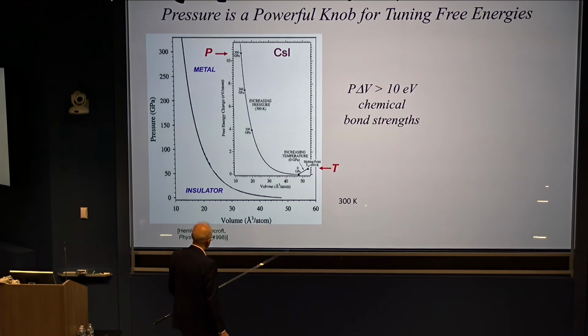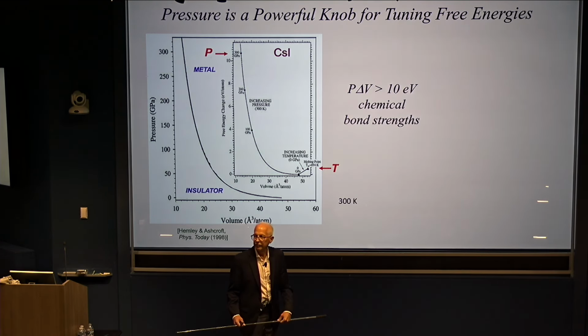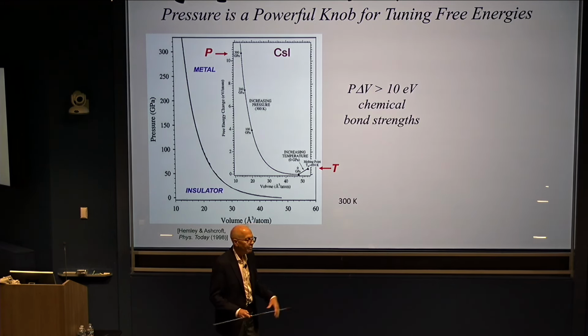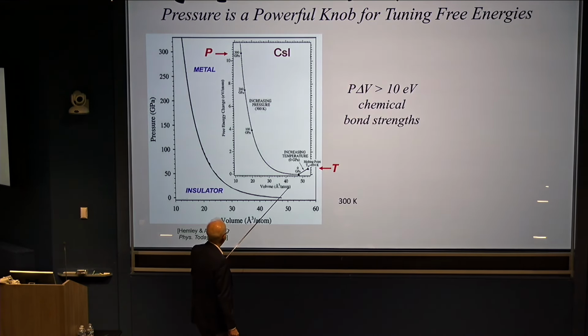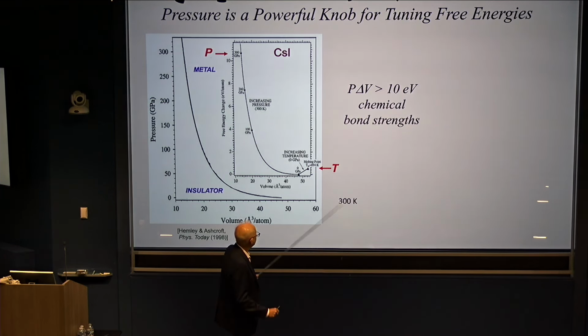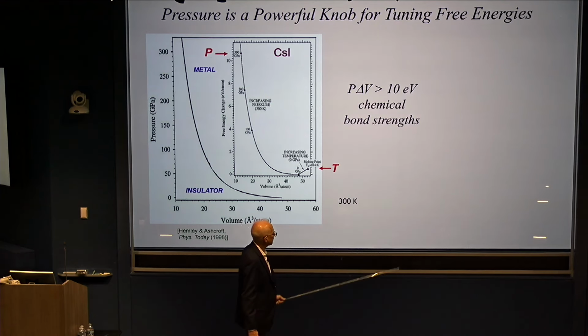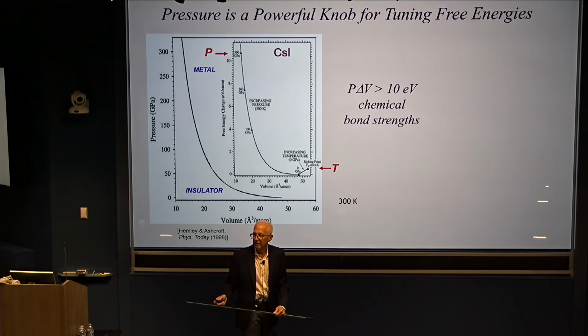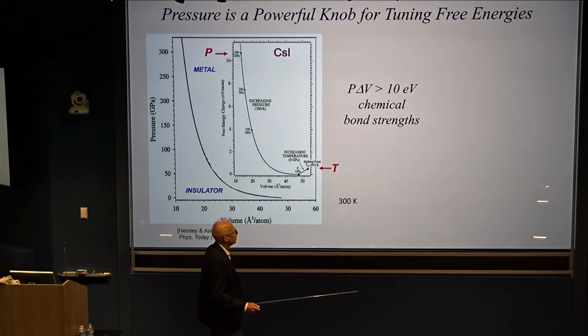Another key point that I want to highlight is the enormous free energy that accompanies the compression of materials now over this range of conditions that we can make or accomplish in the laboratory. So you just take this simple salt, cesium iodide, and you compress it, say, to 300 gigapascals, 3 megabars, and then you integrate that curve, VdP, to get the free energy work. You see that the work is on the order of 10 electron volts, and in many systems is beyond that. So really, pressure-volume work, or the free energy, can exceed bond strength. So obviously, very different chemistry is happening because you're exceeding the strengths of known chemical bonds.